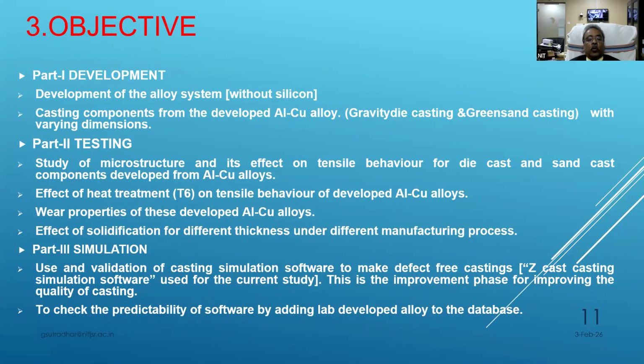After making that component, we did the heat treatment, that is T6, and studied the tensile behavior of the developed aluminum copper alloy. And after that, other wear properties were also found out. So the effect of solidification is also seen in the different parts of a single casting under different manufacturing processes, that is either sand casting or die casting.